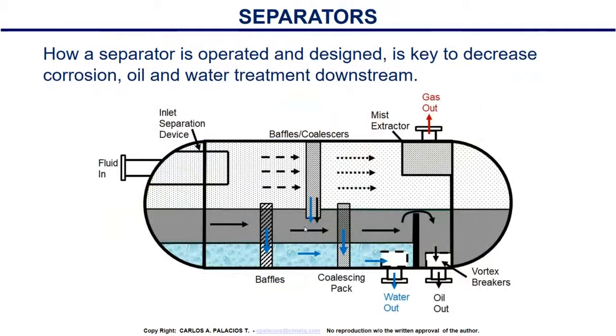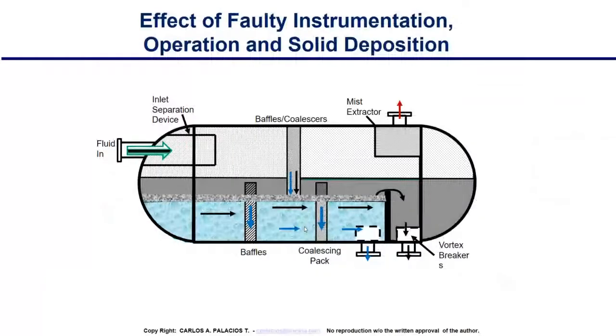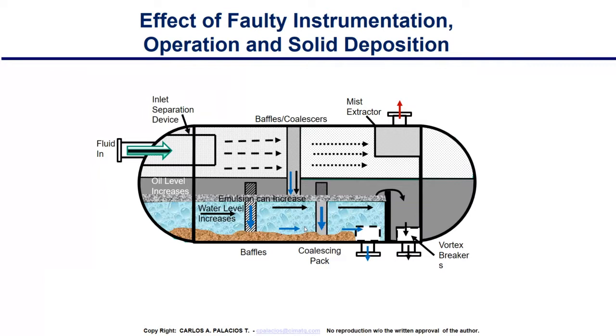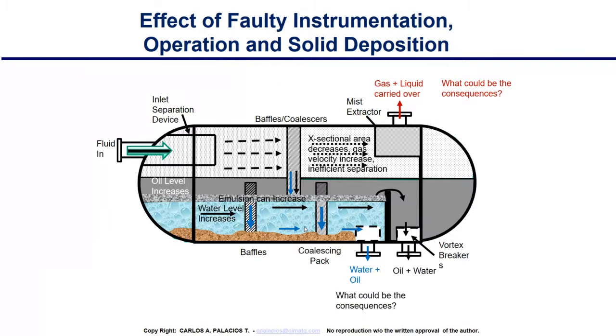Okay, so quickly, flow stations, and I'm going to go quickly because I think I am way out of my time. We go back to the separators. Why is it so important to maintain a good operation of the separator? If we increase the level, or we have sand in the separator, the level increases. If the water level rises, there is more water in the oil. I don't like that. If the level rises, the velocity of the flow is higher, then I'm going to have more oil in the water. We don't like that either. And if this level rises, I'm going to have higher velocity through these baffles. Then the baffles are not going to collect the mist of the liquid, and I'm going to have liquid carryover, because I decrease the cross-sectional area. So therefore, I have issues of corrosion. That's why we need to focus also upstream, as I was mentioning.